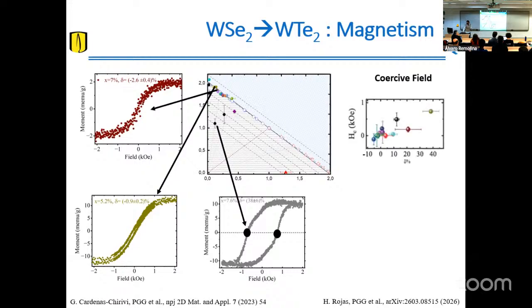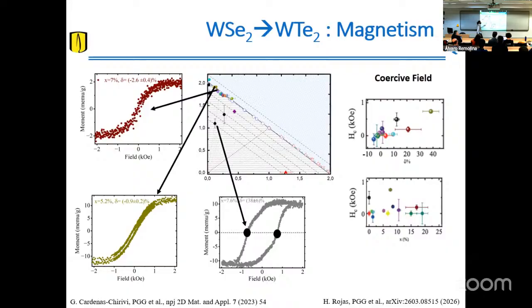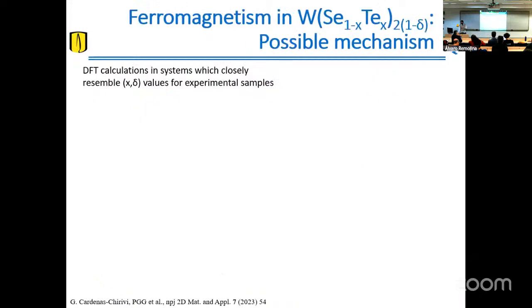And we can see that this coercive field scales with the amount of defects, sorry for the resolution. As the amount of defects in the material grows, the coercive field also grows, which does not correlate very well with the amount of tellurium in the system. All right, so we have a first preliminary conclusion: the amount of defects that we have in the system, and particularly vacancies, are very good for promoting ferromagnetism, and are the driver for this state.